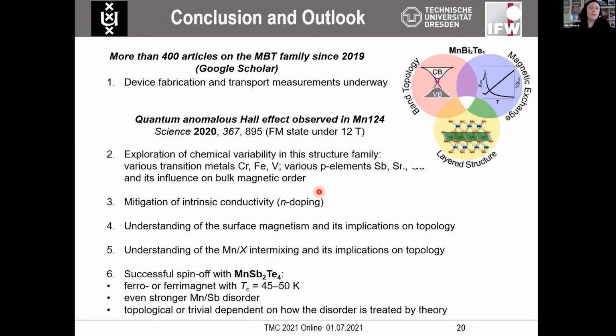Here on my last slide, I summarized what is now ongoing in the MBT family. Let's say on the material side, we have very exciting prospects. So if it will be understood how to control the TCs and the magnetic order in these phases by adding different transition metals or by tuning the intermixing disorder, we will be able to push the critical temperature higher. And if we also understand how to keep the non-trivial topology of the electronic band structure of these phases simultaneously with raising the TC, we will have even better candidates for quantum anomalous Hall effect.